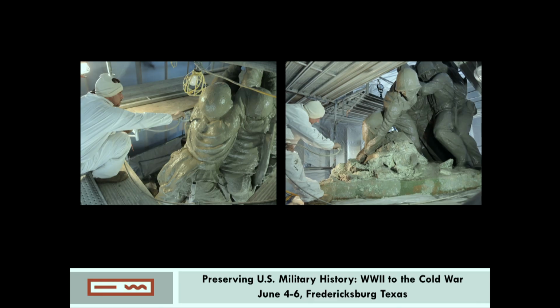A Keim Soldalit coating system was chosen for Iwo Jima due to its compatibility with the substrate repairs and restoration mortars used. Keim coatings are based on a combination of silica sol and potassium silicate binding agents, so they're really appropriate and breathable for concrete. The Keim system is also lightfast and UV resistant, and these were important considerations because the sculpture is right on the parade ground. He's in the sun all the time and all the weather.